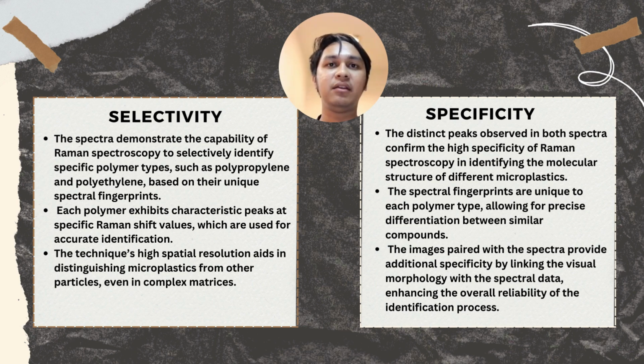Next, we can comment on the Raman spectroscopy in terms of selectivity and specificity. For the selectivity, the spectra demonstrate the capability of Raman spectroscopy to selectively identify specific polymer types, which in this case are polypropylene and polyethylene, because the two different types have two different specific fingerprints. So they exhibit characteristic peaks at different Raman shift values, which are useful for identification. Lastly, both spectra show high resolution, so we can distinguish microplastic from other particles.